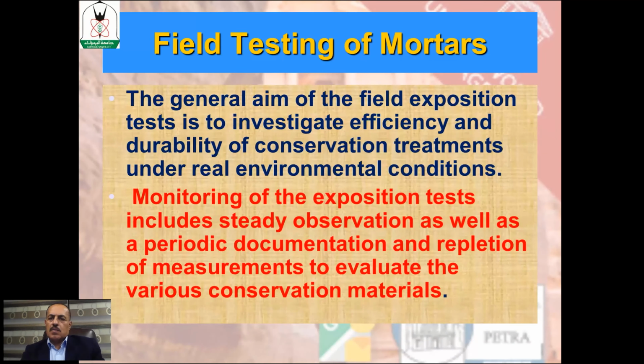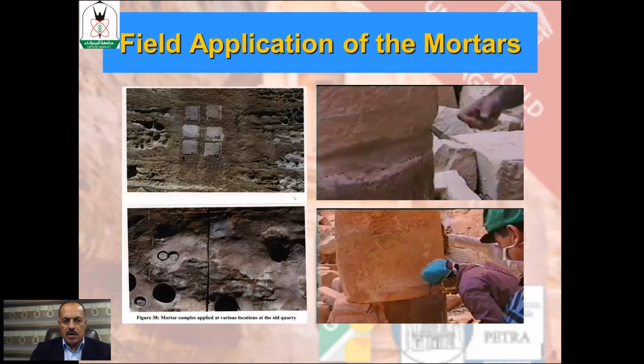And the field testing program, again, was really to investigate the efficiency and durability of the conservation treatments under real environment conditions. Monitoring of the exposition tests includes steady observation as well as periodic documentation of the measurements to evaluate the various conservation materials. And this is part of our test field. We use one of the quarries near Petra as our test field for the application of the different mortar samples, and then try, as much as we can, to imitate the real environment and to understand the behavior of this material under real environmental conditions.